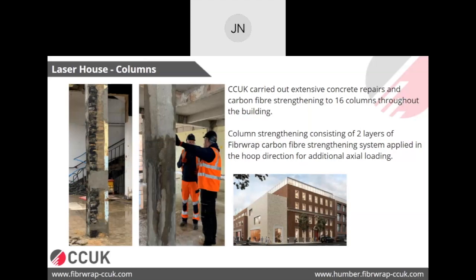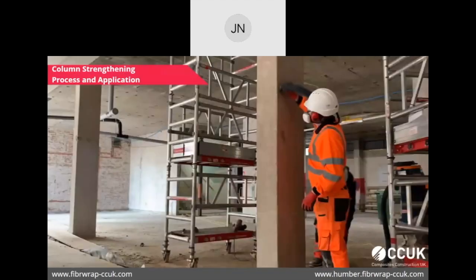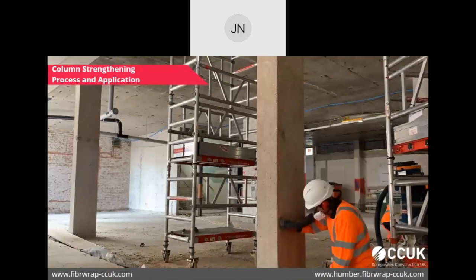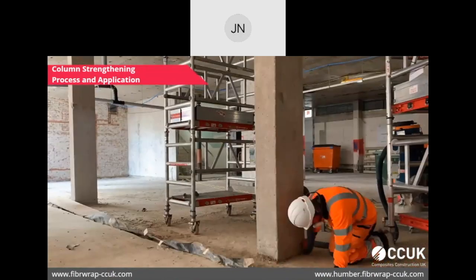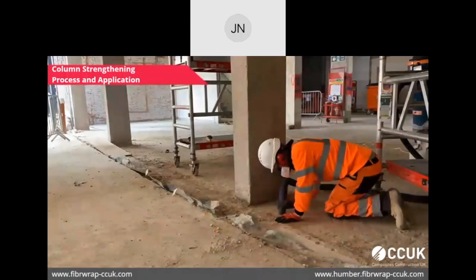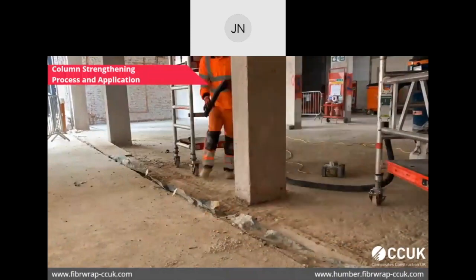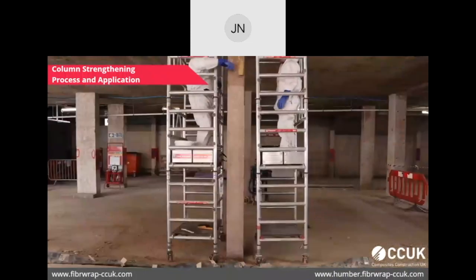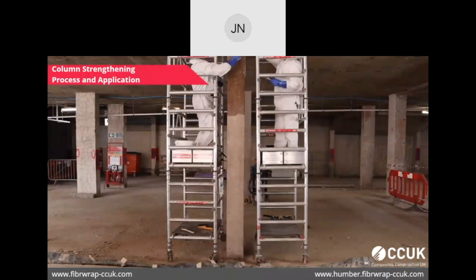So we confined this column, increased the strength of the concrete by confining it, and then ultimately they got the capacity they needed. So it was just a very minimum 2 layers of carbon fiber applied there on each column, and they got the required capacity there. Here is a brief video of column strengthening. So again, same concept there as well. You first prepare the column by grinding and then cleaning. Then you round off the edges and corners to a minimum radius of 20 millimeter.